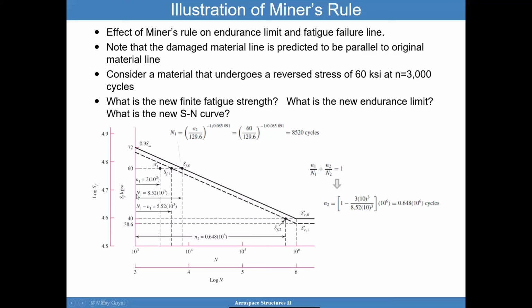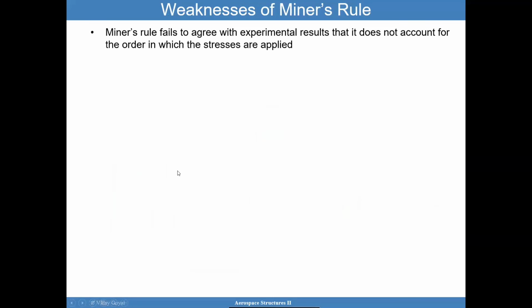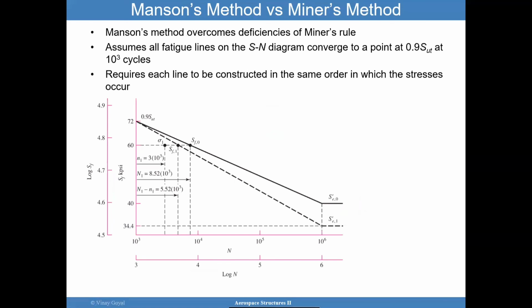And then here again, 8,500 cycles, and then you consume 3,000 cycles. What is the impact to that? That tells you how much this line moves because of that. Again, every time you consume life, this line drops more and more and more. So that's the idea of illustrating Miner's rule. But Miner's rule is not always very accurate.